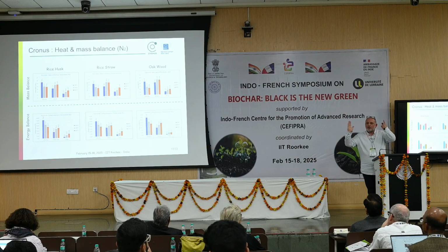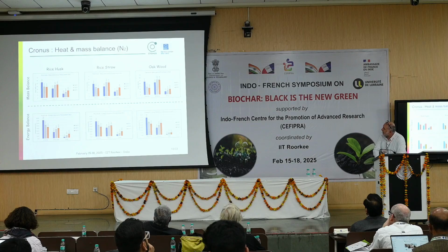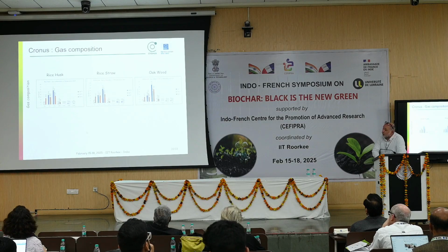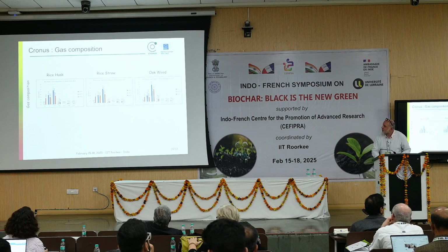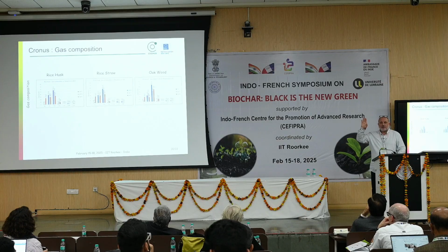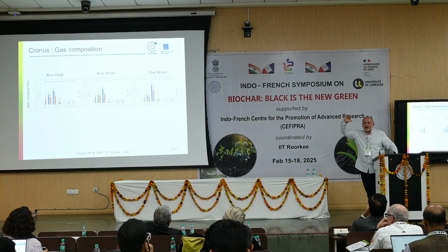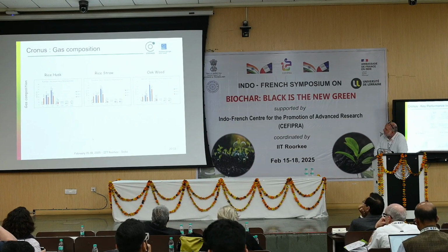We have to choose 3 temperatures: 300, which is the start, 800, which we consider the high temperature, and an intermediate temperature. And also we have the analysis of the gas. So we can analyze the gas composition in order to check what is interesting. In our case, at 800 °C, we produce more hydrogen in relation with the lower temperatures.